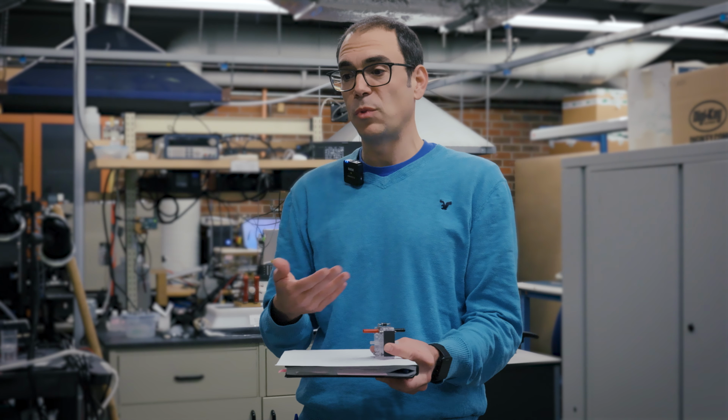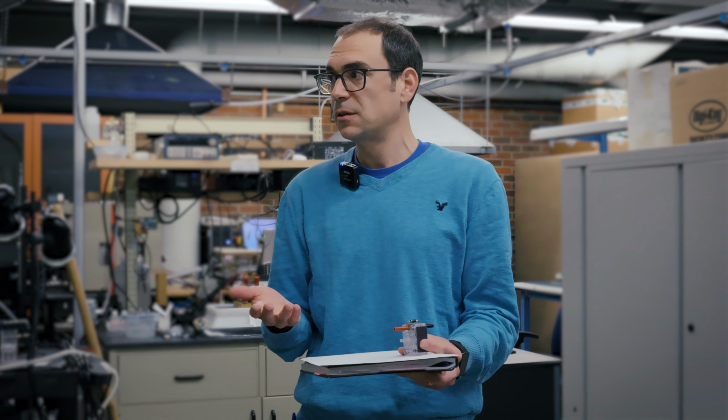Accelerator is based on alkaline electrolysis. The idea of moving to alkaline for us was that in acidic media, there are very few catalysts that can do water splitting efficiently, and you're left with iridium. So usually what you would do is you would mine platinum, and one of the byproducts of platinum mining is iridium. Catalyst companies have written reports discussing the fact that with the current targets that we have from the International Energy Agency, you might not have enough iridium.